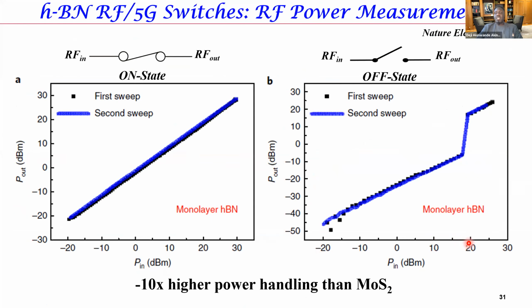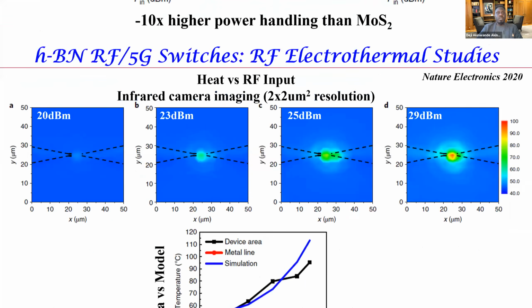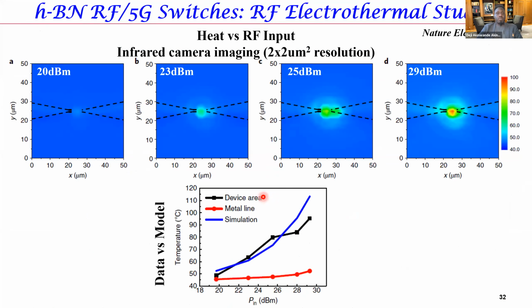So for transceivers, when you're sending signals from, let's say, your smart device to the other devices, you need to be able to send high power because that signal needs to travel a great distance. So 20 dBm is what we can achieve with HBN, which is 10 times more than the power handling of MoS2. So for the sake of time, I'll skip some of this.